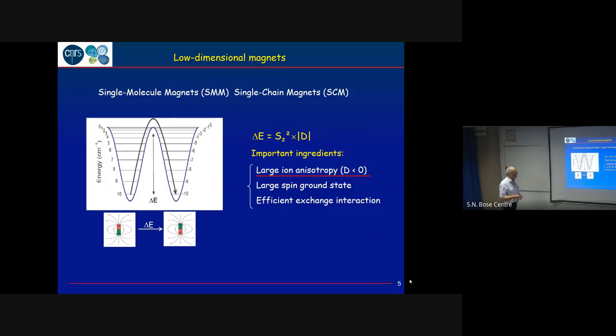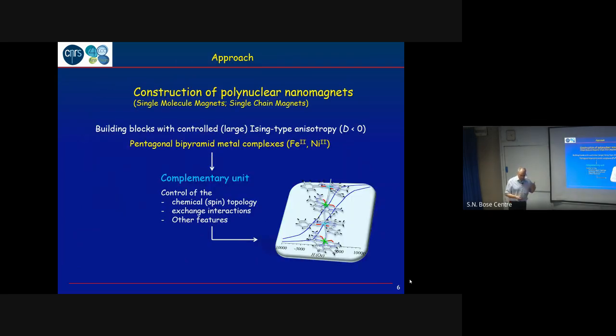And if you have polynuclear systems, you also have to have efficient exchange interaction. So this is a little bit the basics we are using to try to make this system. If now you go back to chemistry, what you need are building blocks with large Ising-type anisotropy. And what we have been developing is systems that have this peculiar geometry, the pentagonal bipyramid.